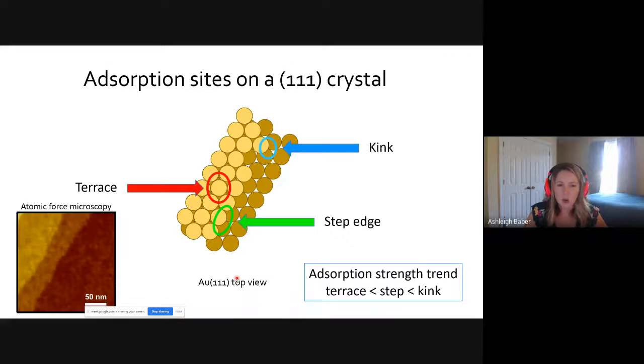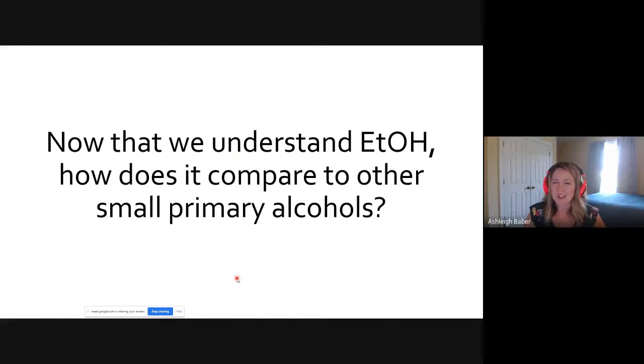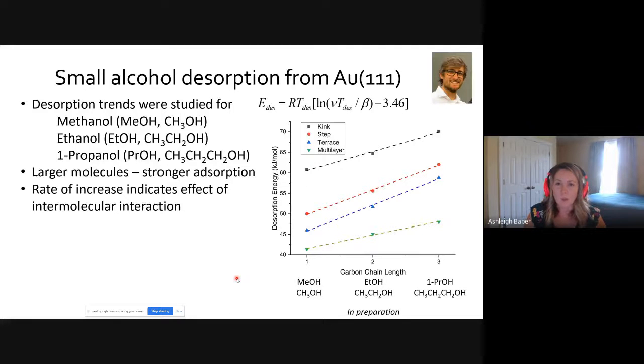Okay. So, I kind of led on that I would only be talking about ethanol, but we have some pretty interesting results looking at some other alcohols as well. I have a current student right now, Eric Maxwell, who has been looking at the series methanol, ethanol, and 1-propanol so far. And as you would expect, here we're looking at desorption energy as a function of the carbon chain length. As these simple alcohols get larger and larger, you expect them to have higher desorption temperatures and therefore larger desorption energies. And that's related by the Redhead first order approximation. And of course, that is in fact what we see. As you have larger molecules, there's a greater interaction between the molecules and the surface, and so they have higher desorption temperatures.